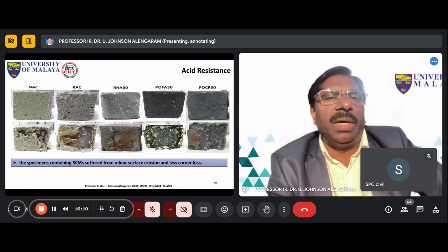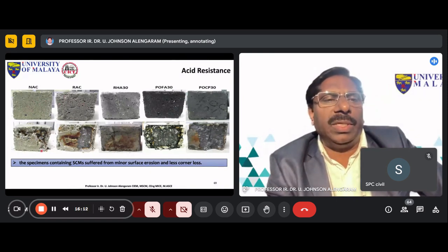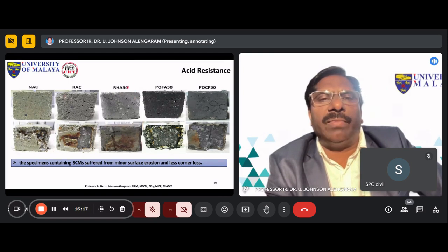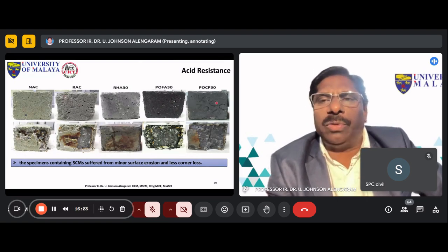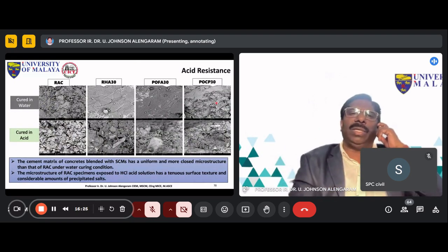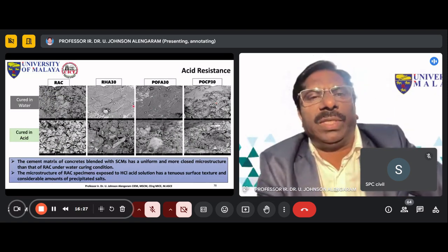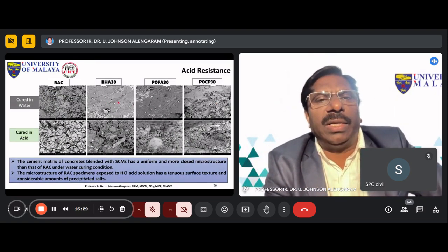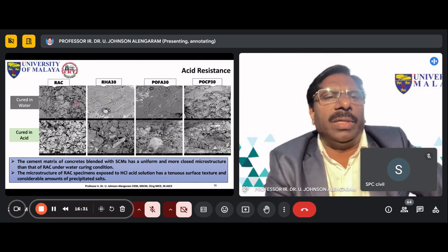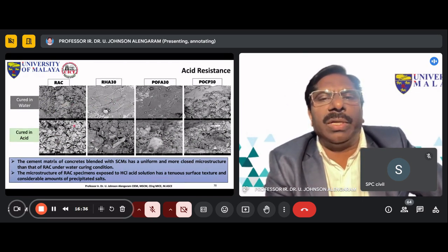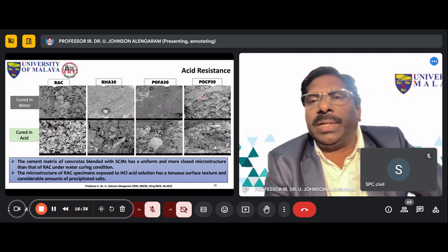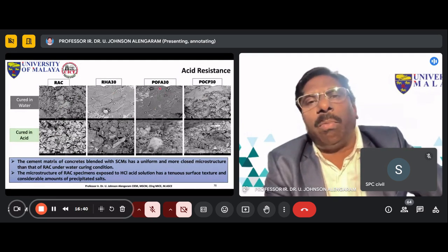Normal aggregate concrete, recycled aggregate concrete, you can see the damage. And you can see the recycled aggregate concrete with the rice husk ash at 30% compared to this. This is much better compared to the other acid resistance, and we can also see the compactness of the structure. Rice husk ash at 30% with recycled aggregate cured in acid, but compared to this deterioration, we can see they are still intact. This is rice husk ash or palm oil fuel ash.